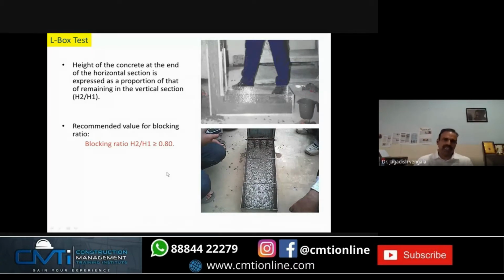If it is less than 0.8, what does that mean? It is taking more time, or the mix is stiff and cannot reach the other end. So many things, or otherwise there is a blocking at the gate while passing through the reinforcement.